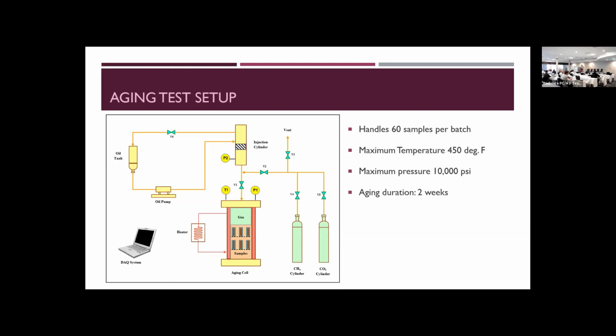Although it's probably not the best way to do aging with CO2, we actually wrote a very intensive paper comparing different methods of aging cement in different cells. This is the most common method that you'll find available. So we use an autoclave, and you can notice here the gas phase on top and the water below. We pump the gas on top, and because of the pressure in the autoclave, the gas starts dissolving in the water. We use a heating system where the water is circulated inside, and by circulating the water, we also accelerate a little bit the dissolution of gas into the water. We also use methane as another gas to control the concentration of CO2. So basically, we have not used air at all in the system for these experiments.